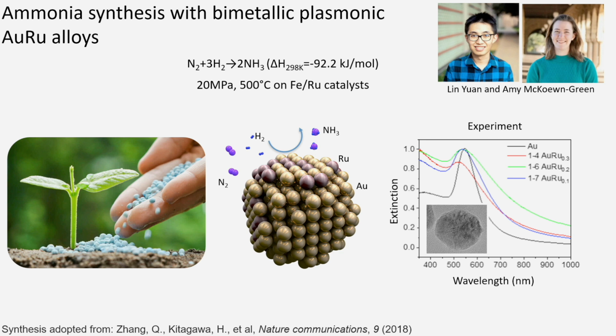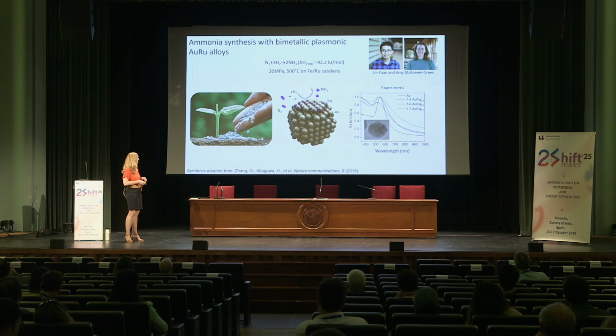And the idea was, can we use the plasmon resonances of gold in this catalytic system to drive ammonia synthesis at room temperature and ambient pressures instead of requiring 20 megapascals of pressure and 500 degrees C? The industrial Haber-Bosch process usually relies on ruthenium and sometimes on iron. So we basically swapped out the iron for this gold. So here you can see the extinction cross-sections where the particle is absorbing light. Again, it's at visible frequencies, in this case between 500 and 600 nanometers.